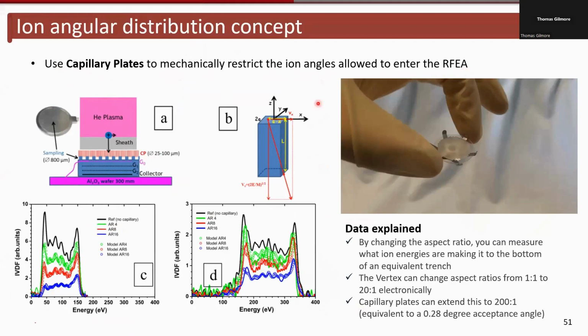This is a screenshot from his paper, and this is a capillary plate. So what is a capillary plate? It's a thin flat disc, usually made of some sort of glass, and there are loads of micro-scale holes drilled into it. For example, this could be 1 millimeter thick, with a big array of 5 micron wide holes drilled into it. So all these holes have an aspect ratio of 200 to 1. The 1,000 microns thickness divided by the 5 microns diameter is 200. So that'll be a 200 to 1 plate.